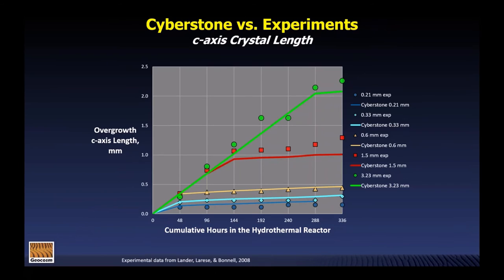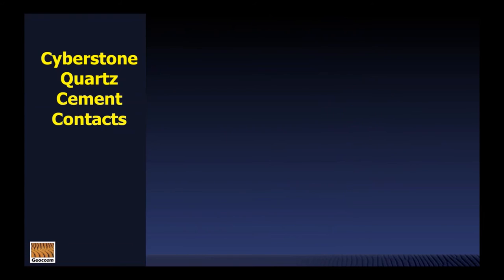So we've tested this model against our experimental work, and what this is showing is a plot similar to what I showed you before, where we looked at the history of crystal growth in those quartz experiments. These points represent data from the experiments, and the solid lines show our simulation results. So I think you can see that the model's doing a very good job of getting this quartz growth rate effect as a function of the development of the euhedral faces as a function of the area of nucleation.